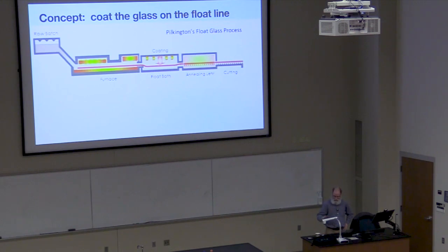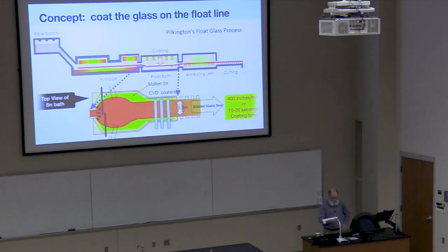So here's our float glass process again. You might remember I said, in here we're forming the glass into a sheet. By the time it gets here, it's in a sheet, and it's a well-defined thickness. So if we look at that tin bath from the top, here's where the glass comes in. I've kind of expanded the length. The glass comes in and pours over this spout, and they said it's like molasses, so it kind of spreads out. These are those knurled machines that help bring it back to the right thickness.